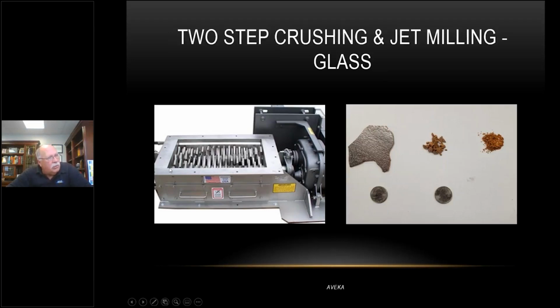And this is the type of crusher that we used. It's a finger crusher, and basically you pour that material in there, and those fingers just crush that glass up to get this feed material to our jet mill. Sheets that are much bigger than what you're seeing here, I mean, they might be feet in diameter, going to a nice feed that we can now feed into our system, ultimately to get the final product that comes out of here.